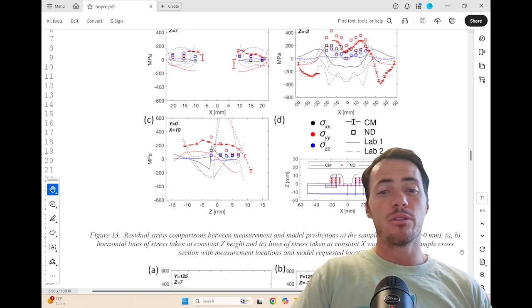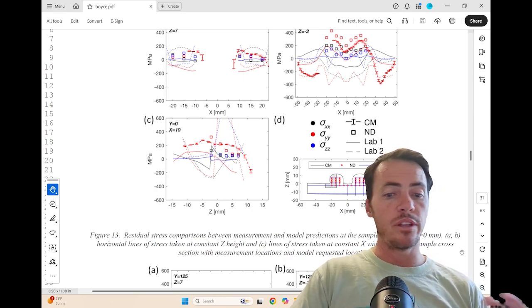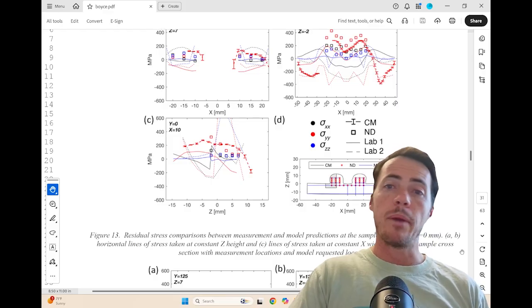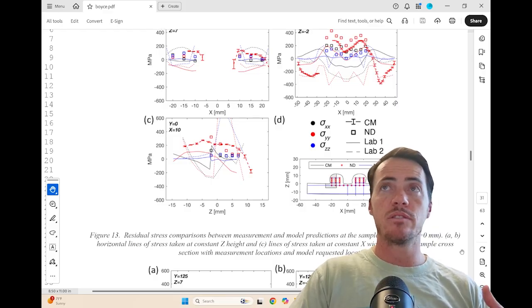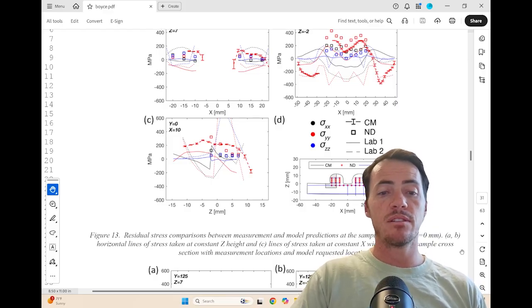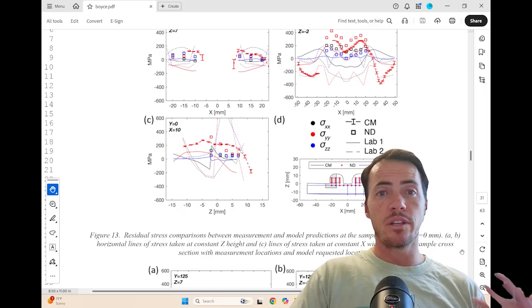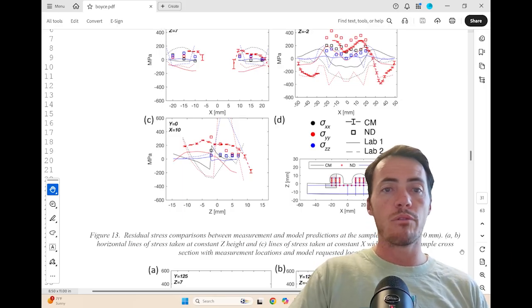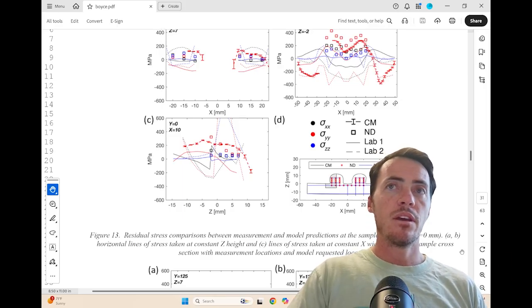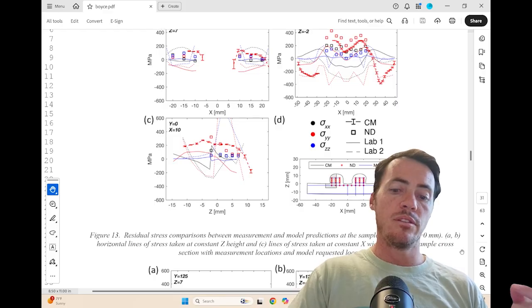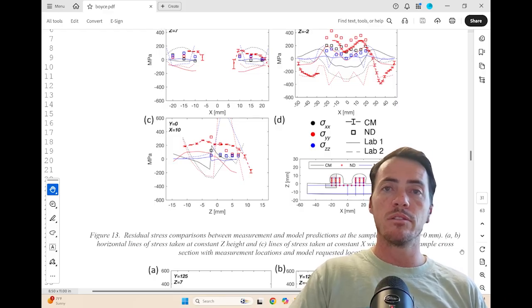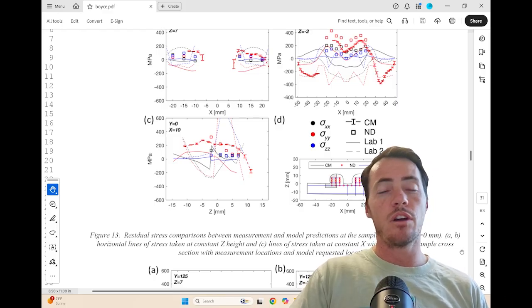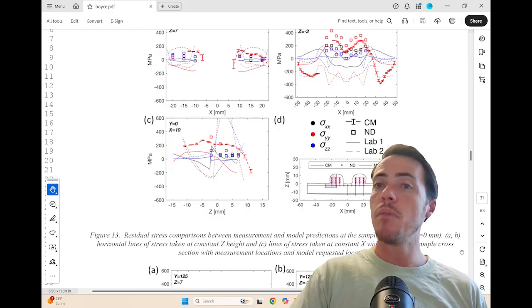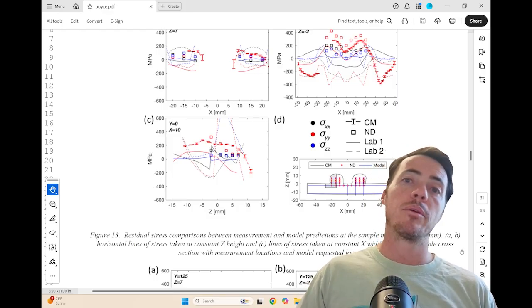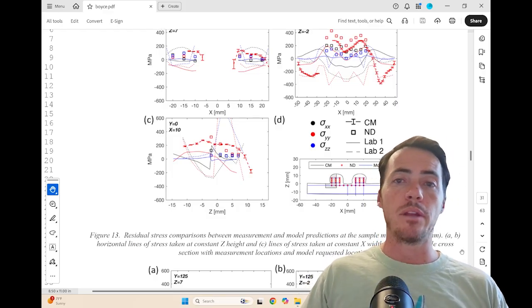But our models for predicting residual stress really kind of fall apart. One of them actually predicted stress of the wrong sign, suggesting that it was compressive when it was actually tensile. Another one over-predicted the stress by a factor of 4 or 5 times. So in other words, even though our models can predict the temperature and the distortion relatively well, they are not doing a good job of predicting the residual stress. And that may be really important depending on the application of your wire arc additively manufactured part.